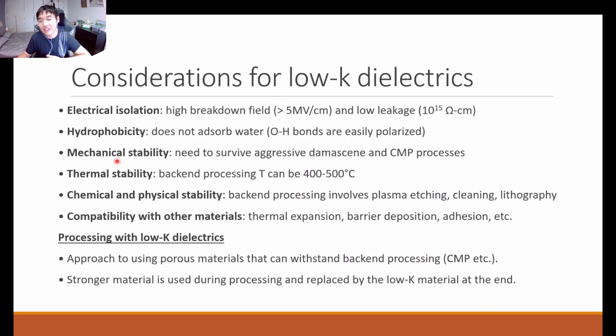In addition, we also need mechanical stability of your material, because remember your back end of line dielectric materials often need to go through very aggressive damascene and mechanical polishing processes. So these require a certain mechanical stability and strength of the material. In addition, it also needs to be thermally stable. Your polymer, for example, should not have too low a glass transition temperature or too low decomposition temperature, because our back end processing temperatures can also be elevated as well. It also needs to be chemically and physically stable to processes like plasma etching, cleaning, lithography. It mustn't degrade, for example, under UV exposure in the lithography step, or it mustn't be too easily reacting with, let's say, your plasma cleaning steps as well.